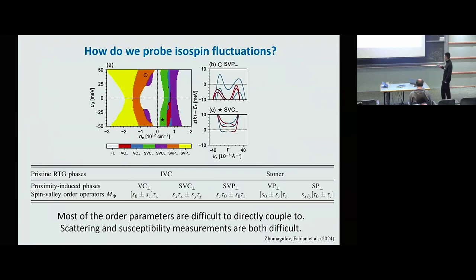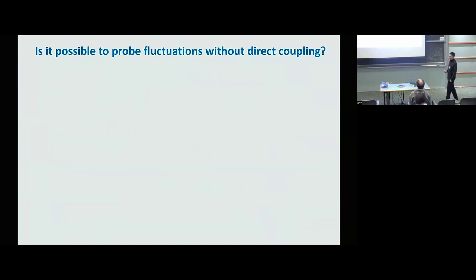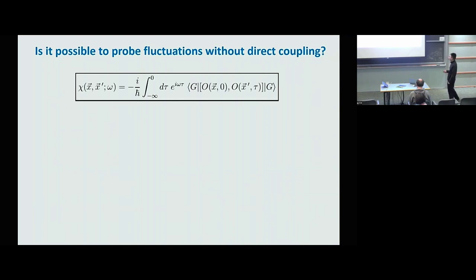And in addition, scattering measurement is just generally hard for 2D layers. They are very powerful for studying bulk systems, but the cross-section is just too weak, too small for a thin 2D layer. So it looks like our third challenge is actually even harder or even more serious for these flatband graphene systems if we want to probe fluctuations. And this motivates us to ask, is it possible to probe fluctuations without directly coupling to them? And the answer is actually, well, at least in principle, it's possible.